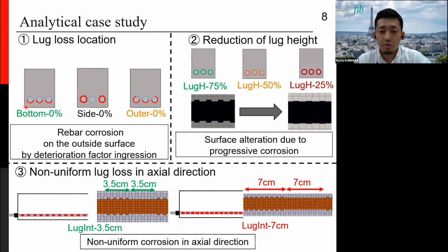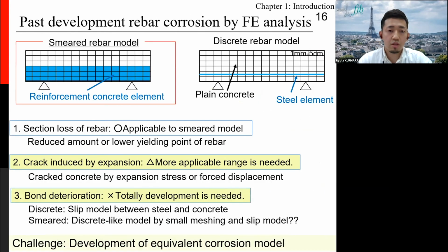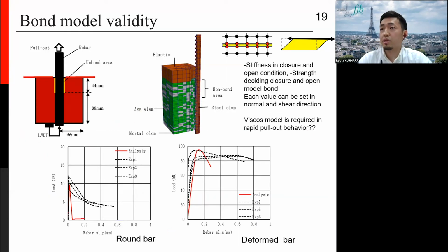For the influence of the rebar diameter, I didn't conduct it for the beam analysis, but for a simple analysis, the tensile test and reproducing analysis is conducted like this. I conducted both the experiment and the analysis, and as one parameter, I set the rebar diameter. Of course, the lower the rebar diameter, the lower the lug height, but the trend is almost the same. If the lug height is lower than 50% of the standard, the tensile resistance strength was lower, basically as a trend.